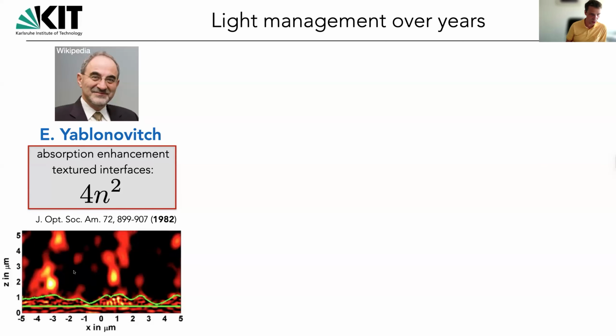And generally also studying how given textures behave when they interact with light with these structures. So these textures for a long time had been fabricated in a kind of stochastic manner by putting silicon substrates into a weakly acidic solution and then etching down these materials. These textures have been implemented into silicon materials where they have then also been used for the purpose of light management.